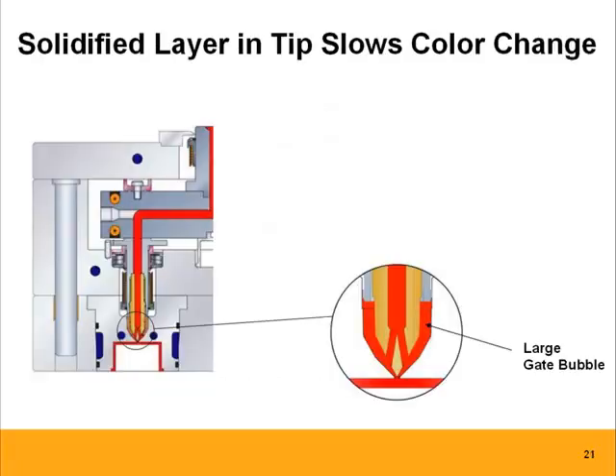The other portion of the hot runner that's very important from a color change point of view is the interface, or the gate detail, between the hot nozzle and the cavity itself. You see here a blown up version of just that detail in the front. Pretty much with every hot runner system, you need to have some kind of gate bubble in the front. This acts as an insulator, protecting the hot tip on the inside from the cold steel. If you were touching this tip right to steel, it would be losing too much heat, and the operating window of a hot runner system would be vastly reduced.